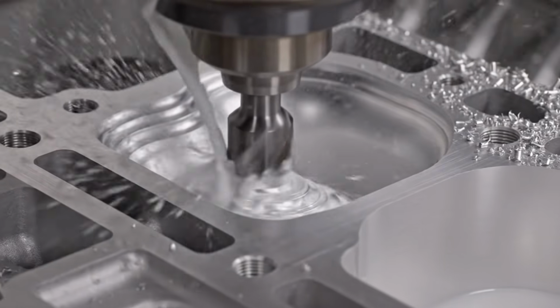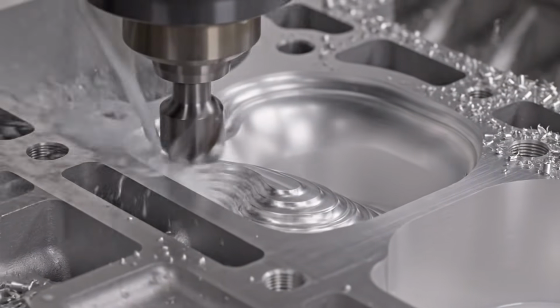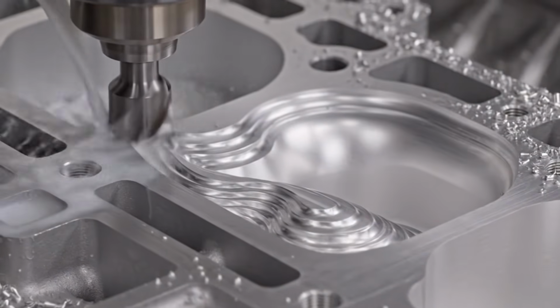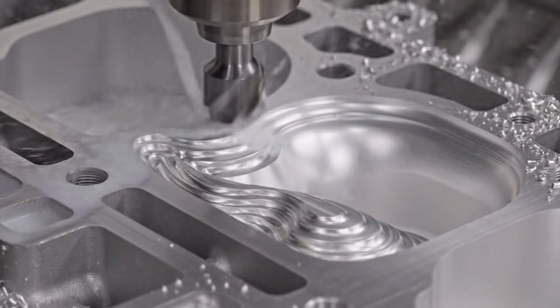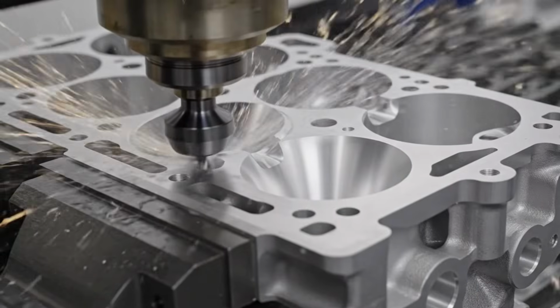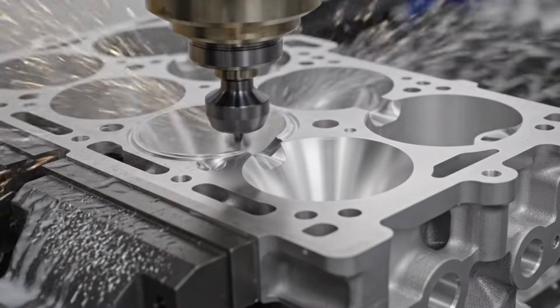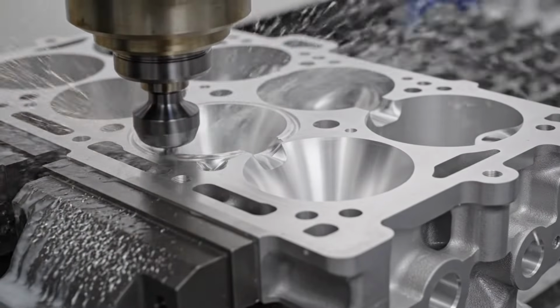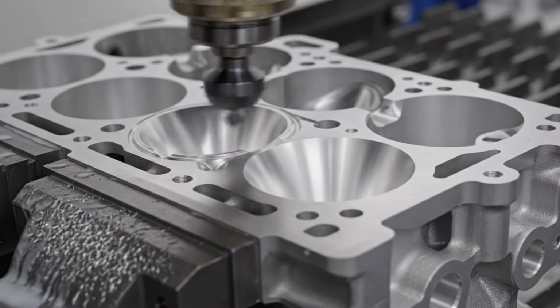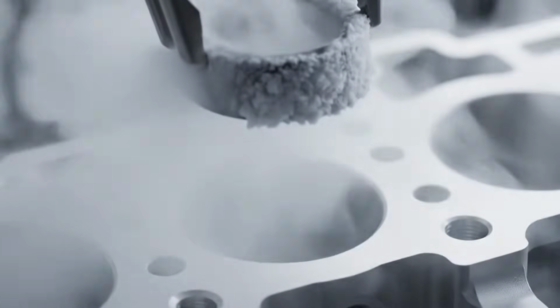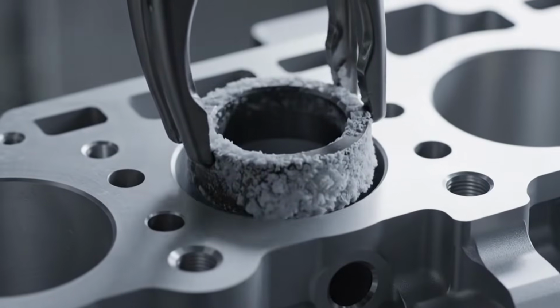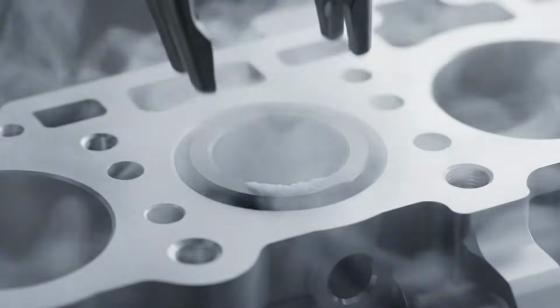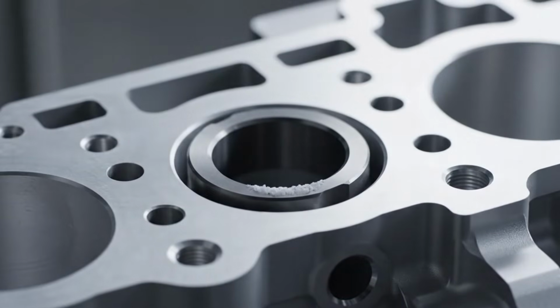A ball nose end mill follows a complex three-dimensional path, creating smooth flowing contours that maximize volumetric efficiency. The chamber has a complex squish band geometry that creates turbulence for efficient combustion. Each insert is cooled with liquid nitrogen to minus 320 degrees Fahrenheit, causing thermal contraction.